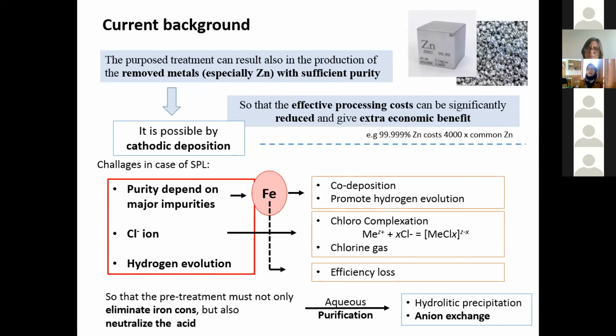The current background of this paper is that we did electrodeposition of zinc from the SPL to recover zinc. We know that electrodeposition is widely used to recover zinc from solutions around the world; 80% of zinc production comes from electrodeposition. So why don't we use it for the SPL as well? But there are still a lot of problems. As we know, zinc has a far more negative potential than hydrogen, so the problem will always be hydrogen reduction accompanying the main reaction that we want.